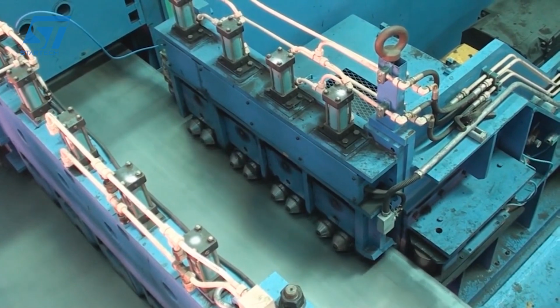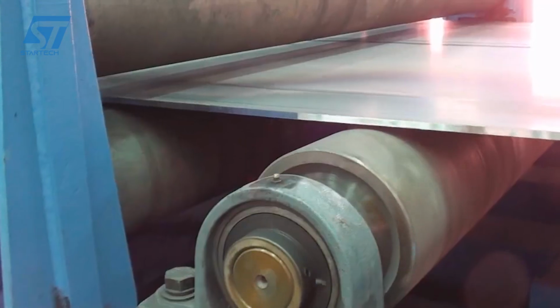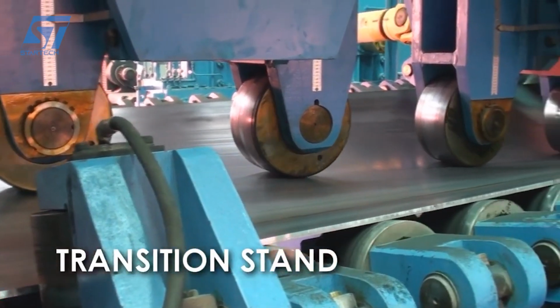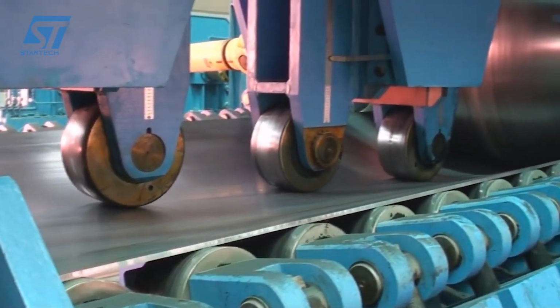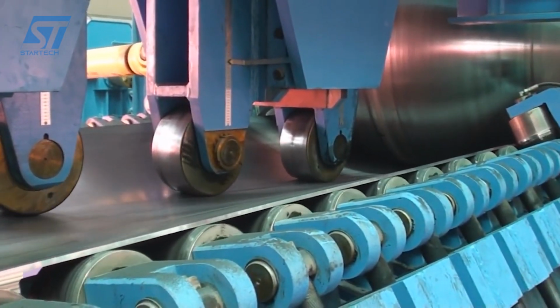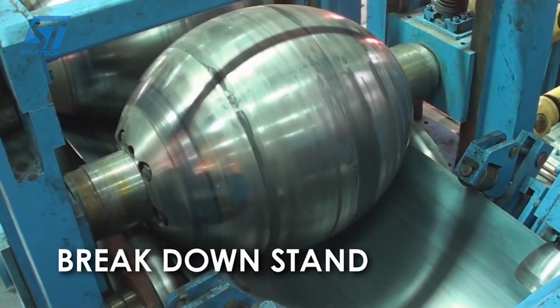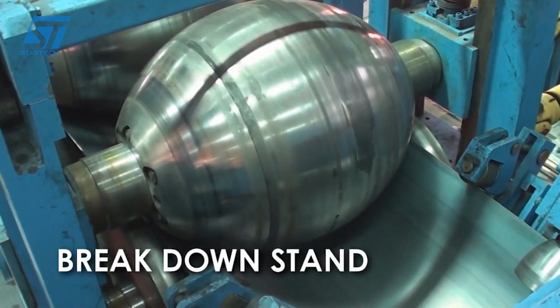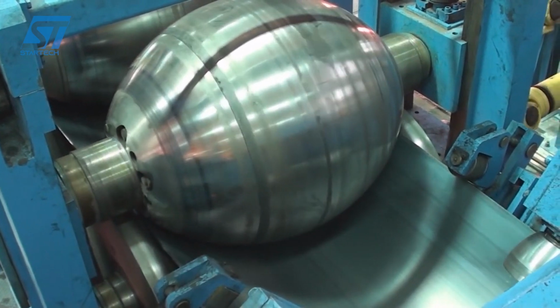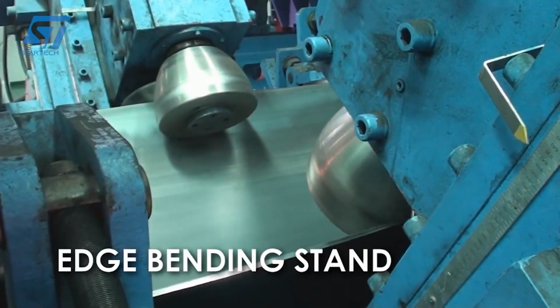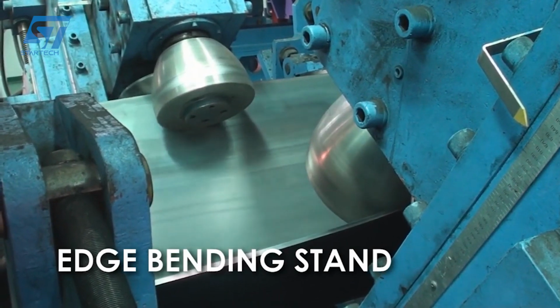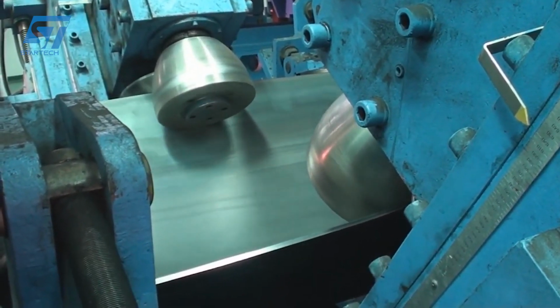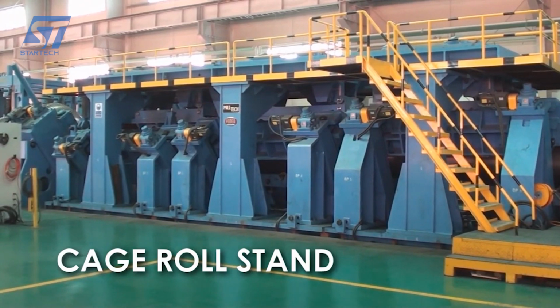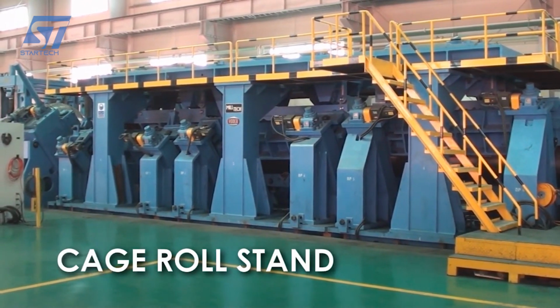Conventional forming methods roll the material in separate steps and use pressing force. The Yoder cage forming system forms steel strip continuously with smooth transitions and minimal effort. As a result, the material is actually guided through the forming plant with a uniform but extremely small shape change in each small step of the strip. The advantage of the Yoder cage forming system is that it enables continuous and smooth forming. Unlike traditional methods that use pressure and discrete roll steps, it minimizes unwanted stress and deformation on the material.